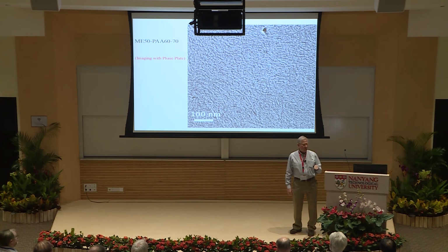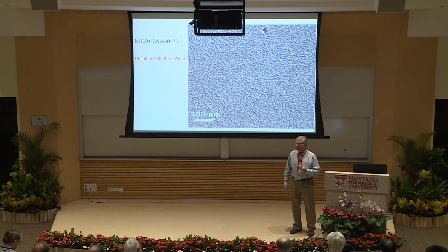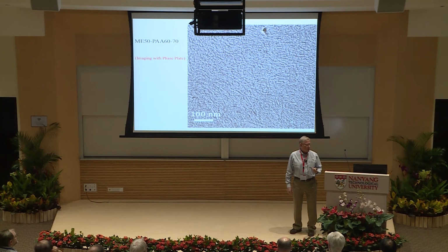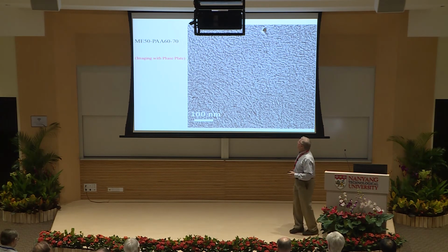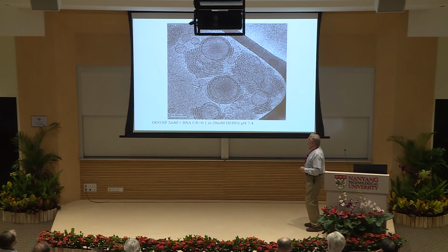will try to explain why we lose transfectionability when we add the blood components. So what we thought would be the problem is that some of the components of the blood actually interact much stronger with the polyelectrolytes, and by doing this, destroy the lipid complexes. And this is really the case.